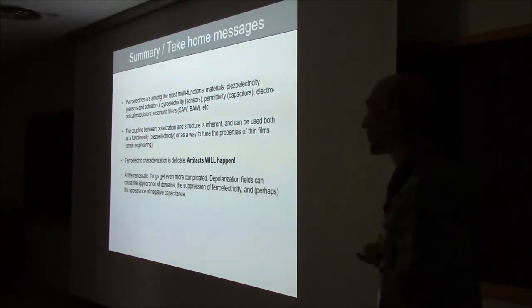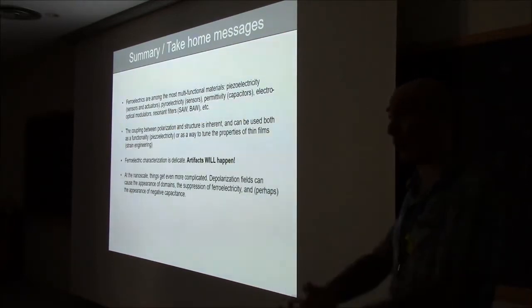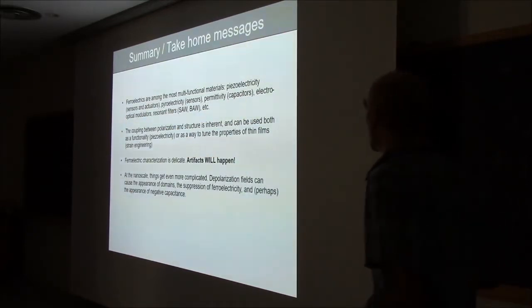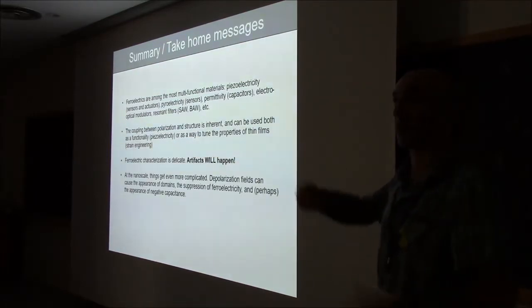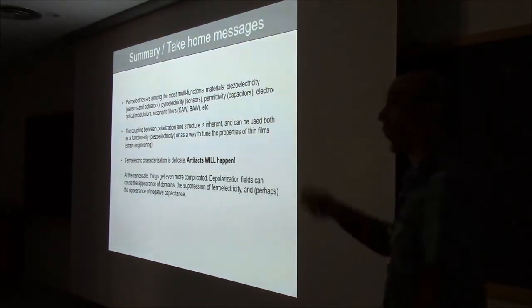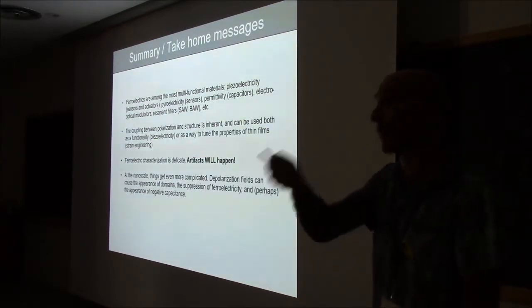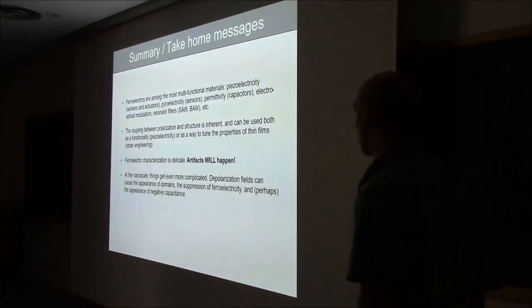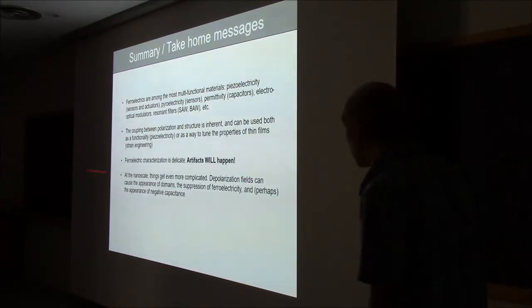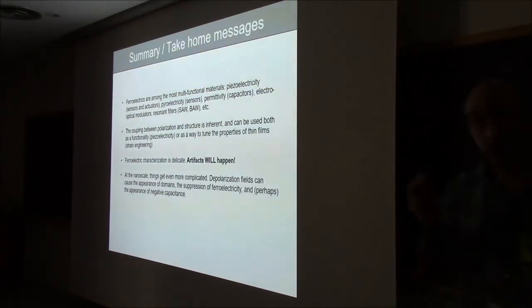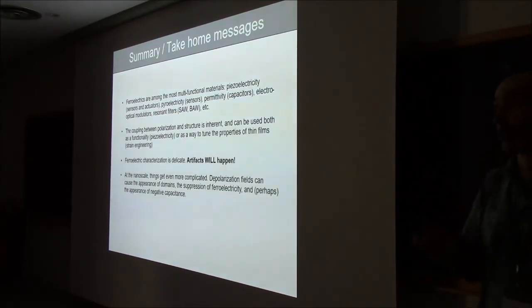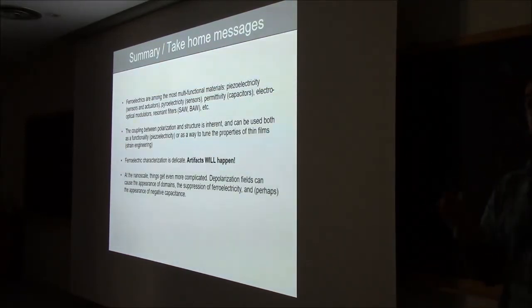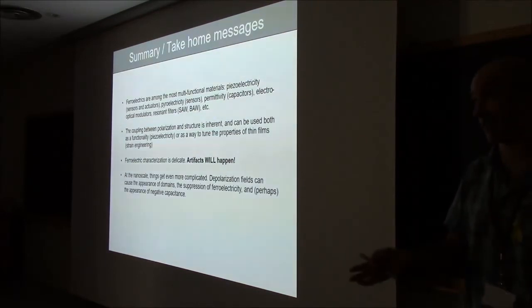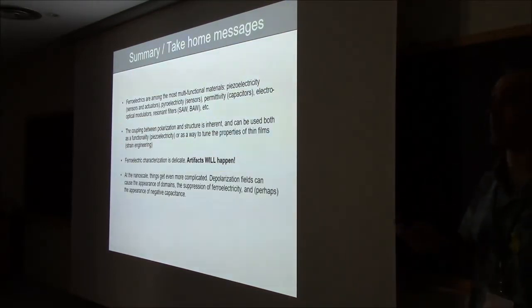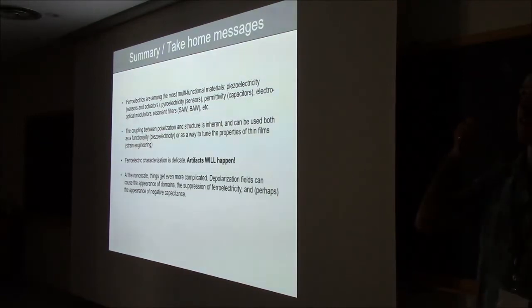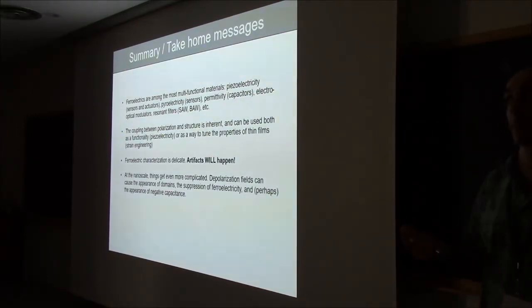The coupling between polarization and structure is inherent because all ferroelectrics are piezoelectric, and you can use that both as a function in itself, as in you can exploit the piezoelectricity, or as a way to tune the properties of your ferroelectric thin film via strain engineering. Okay? The ferroelectric characterization is a bit of an art. You need to know what you're doing. And if you don't know what you're doing, if you're new to the field, really I strongly encourage you to talk to someone who does. Especially be aware of ferroelectric hysteresis loops and super high capacitance if your material is semiconducting, if it's leaking.